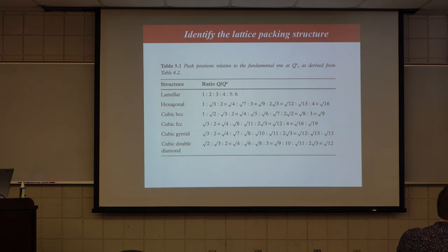Ben, please. Yeah, like the specifics for the structure factor. Yeah. So if you take your block polymer and shine X-ray, assuming it's highly ordered like this case, you would have multiple peaks showing up. That's expected. From the first peak, you can identify the packing distance, what's the distance between the domains, right? But more useful is that you can identify if you form spherical domains that are body-centered cubic, or cylindrical domains that adopt a different packing, or lamella.